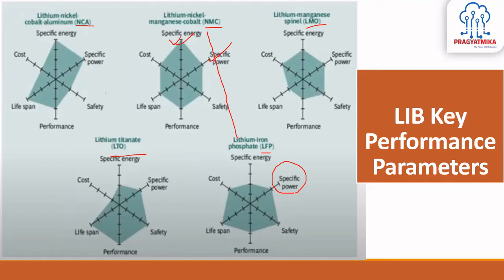If I compare the NCA and NMC chemistry, NCA is cheaper in cost because of the use of aluminum. On safety, it is a very unsafe battery chemistry. The thermal runaway temperature is just around 150 degrees centigrade, whereas for NMC it is 210 degrees centigrade, and it goes to around 300 degrees centigrade for the LFP.